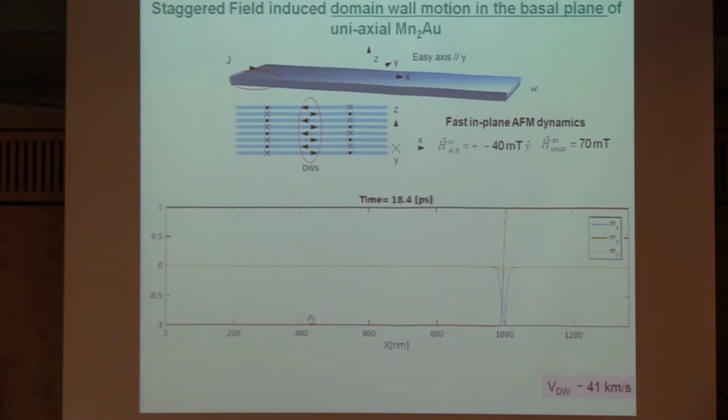Moreover, what they also show is that this motion can be described by a Lorentz invariant theory. And one result of this Lorentz invariance is that the domain wall width is reduced, a kind of length contraction, as you reach a critical velocity. And as you can see in the simulation, we started with a much wider domain wall in a steady state situation, and it becomes very narrow when it accelerates and reaches its steady state velocity.